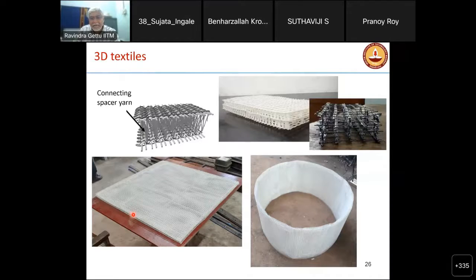So you have to have a flowable binder that will penetrate. This is very important to know: we should have the binder or the matrix that can flow between the yarns. Otherwise, you will not get good bonding. There will be failure due to pull off, and there will be slipping. So the challenge in making the binder is a binder that can flow, can penetrate into all these yarns, so that the bond is very good. If you don't have bond, then you will have slip failure. So this is very, very important. Making the reinforcement and also making the appropriate binder is very, very important.